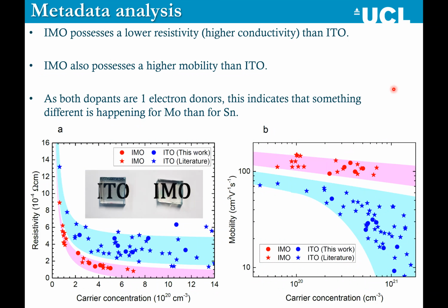surveys that we did. And what we saw was that actually IMO has a much lower resistivity or higher conductivity than ITO. It possesses a higher mobility than ITO. And this is across the board. Every single sample for sample, IMO beats ITO.